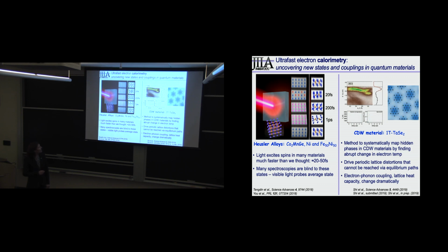In a whole range of magnetic materials, what we're seeing is that ultrafast lasers can directly excite spins on very fast timescales. In fact, I forgot to update this: it's about femtoseconds to attoseconds now. And the reason it wasn't seen is not that it wasn't happening, but that a lot of spectroscopies measure the average excitation in the band in a material, and so they average. If you have a high non-equilibrium excitation, you just can't see it with traditional magneto-optic spectroscopy.